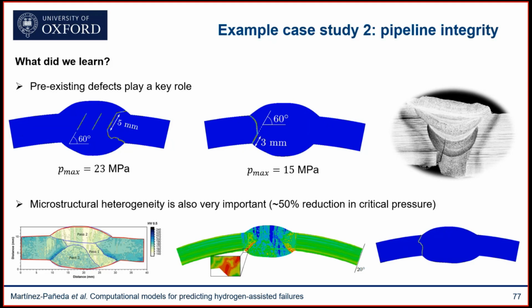And the other aspect is, of course, the role of the microstructure. We know that the microstructure can be very heterogeneous. So in this case, this is a collaboration with EPRI, I forgot to say, so they have very nice hardness maps. We can use these hardness maps to quantify the heterogeneity of the microstructure. And then we can make our properties depend on this heterogeneity.